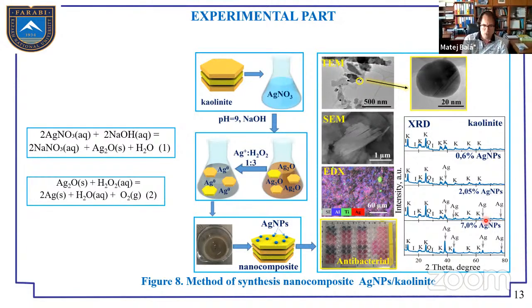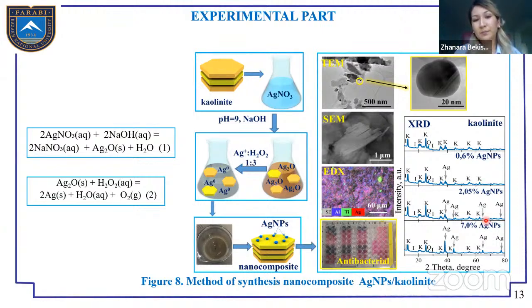Okay, and here you say that it's actually a 2-step process. At first you produce silver oxide and then it is turned into elemental silver. Do you have any spectroscopic proof of the presence of the silver oxide? No. Okay, so it's just based on the literature and the mechanism of how this reaction should run. Yeah, we analyzed and chose this method because silver oxide is not stable, and it is difficult to precipitate on the support. It was immediately basified, and after that reduced. It's not for a long time.